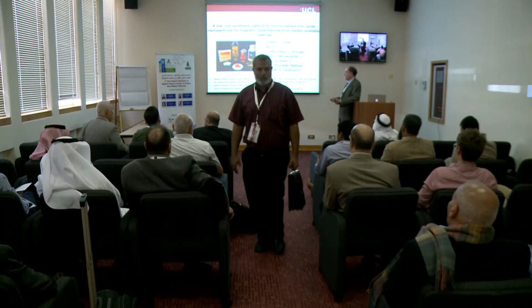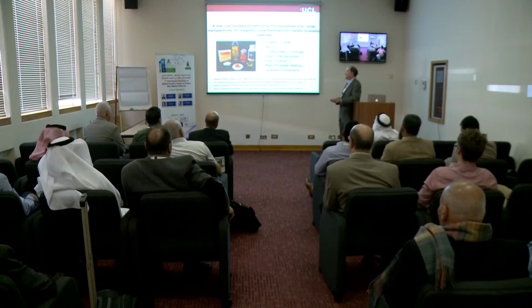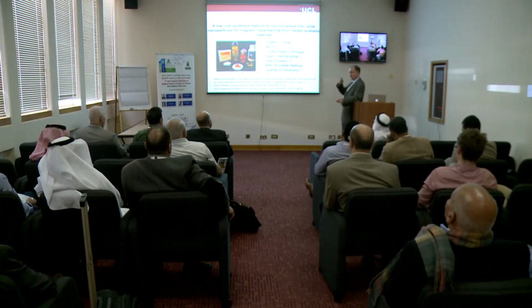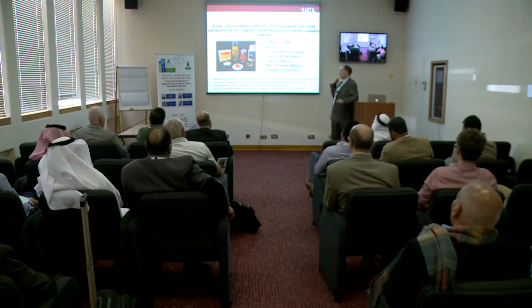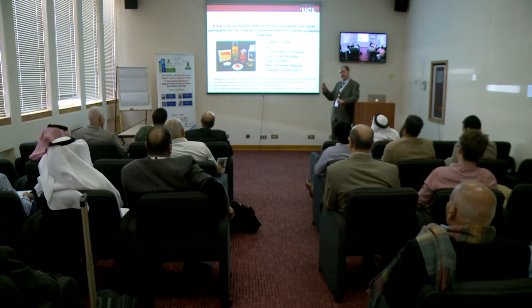The last thing I want to talk about is something we've looked at for healthcare, in particular to try and make metal oxide nanoparticles for use as anti-cancer agents. It's potentially a new way of treating cancer by using magnetic hyperthermia. And the way in which this works is the magnetic nanoparticles go into your body, you can apply an external magnetic field and you heat the nanoparticles up. If you can localize those nanoparticles in the region of a tumour, then that can help to kill the tumour. Or, which we've looked at, if you can tag the iron oxide nanoparticles with a cancer recognition fragment, they will swim in the body to the point that you want to localize, and then you can apply the external magnetic field and kill the particles.